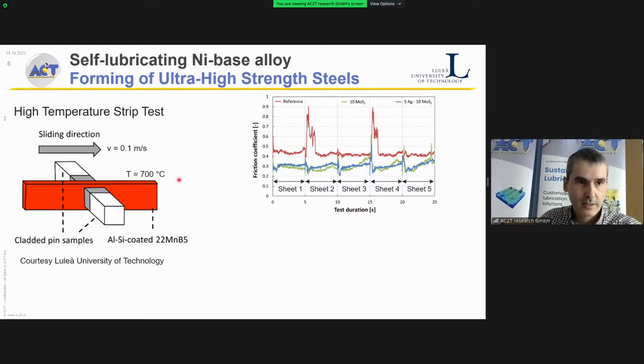a close to reality tribometer that is available at Luleå University of Technology in Sweden. In this case, we have a strip test with aluminum-silicon coated ultra high strength steel at 700 degrees, and we always do a single pass, replace the sheet and use a new one. You can see here the results, and you can see that when we use a reference, in this case a nickel-based material without any solid lubricant, friction is high, and also we have these break-ins into the aluminum-silicon coating, which spikes friction close to 1.